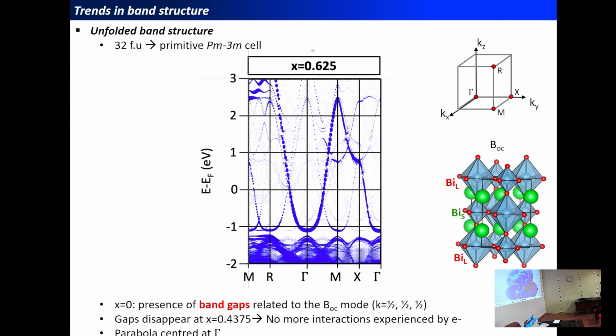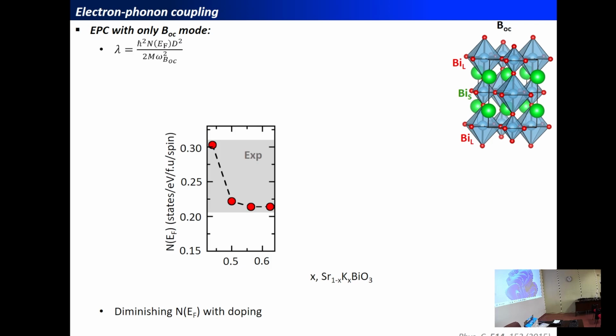So now we have seen that there is a phonon mode that is strongly coupled to the electronic structure in the material. So in principle, to compute the electron-phonon coupling, we should consider all the phonons in the material, but this we cannot do because we are using a very, very large supercell with 32 formula units, so it's impossible to do a feasible calculation for the phonon dispersion curve and so on. But in this system, we have observed that there is one phonon that is strongly coupled to the electronic structure. That's the breathing distortion that is producing the charge ordering in the material. And so we will try to compute the electron-phonon coupling associated with this phonon mode.